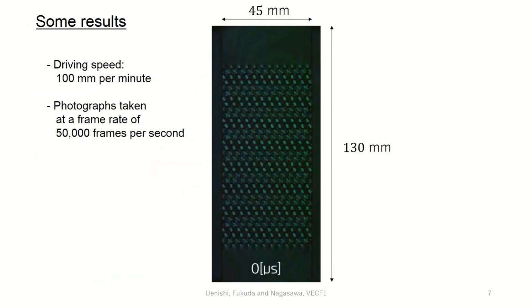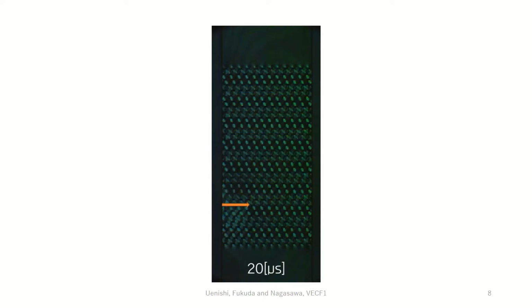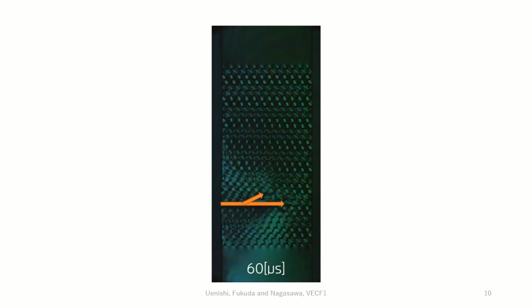This picture shows the isochromatic fringe patterns or contours of the maximum in-plane shear stress dynamically developed in the specimen, just before the primary fracture is initiated, time 0. The driving speed in this case is 100 mm per minute and the following photographs are taken at a frame rate of 50,000 frames per second. Due to the action of the external load, the primary fracture develops. It moves from left to right. Also, branching of the primary fracture can be observed in this experiment.